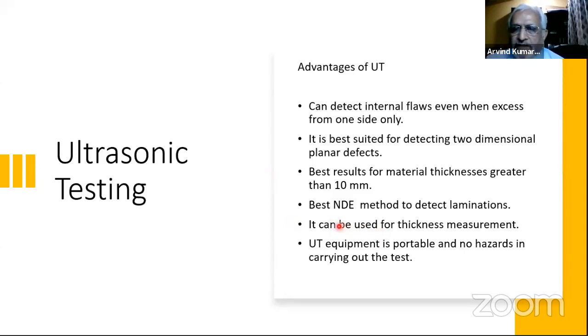Then this is the best method to detect laminations. We know the technique is used very widely to detect laminations. There are various codes available, such as ASTM A435 and A578, which give the ways to do the lamination check and what extent of lamination can be accepted. It is also widely used for thickness measurement. That is what Mr. Jain had mentioned in the beginning. You have thickness measurements in ship hull structures, where you have so many service providers approved by the class who regularly do thickness checking and monitor the diminution of the material.